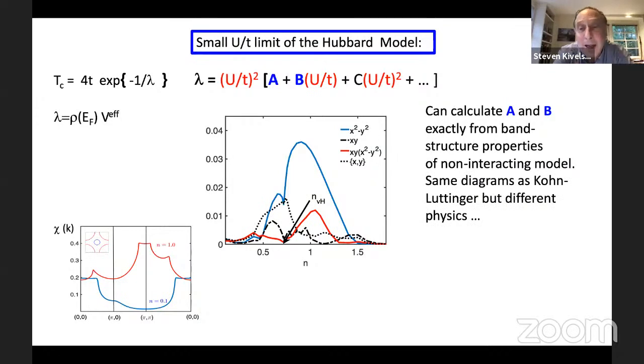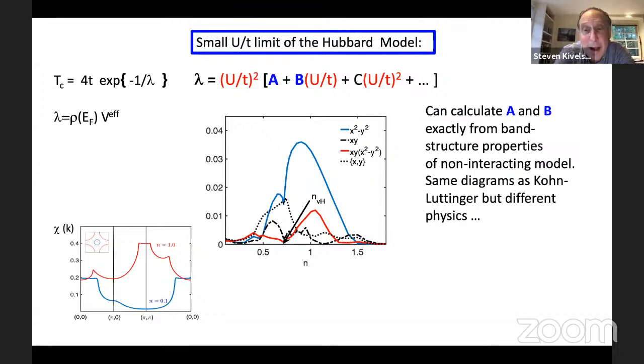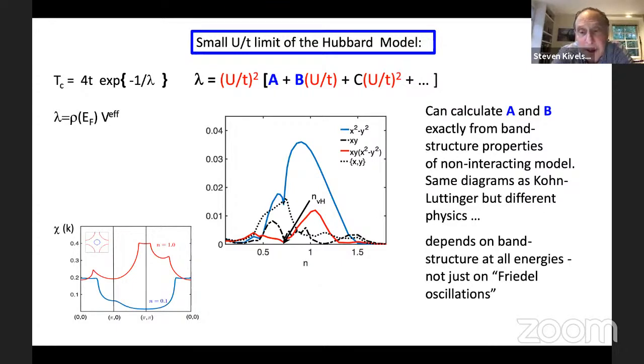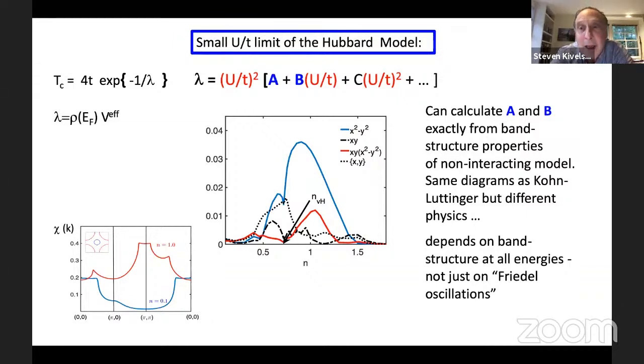This leads to an aside: the diagrams analyzed in this way are more or less the same as those analyzed by Kohn and Luttinger when they discussed this mechanism of superconductivity. There is a difference in emphasis — they focused on the effect of a sharp Fermi surface and Friedel oscillations as the source of pairing. That's not what's going on here. What's going on here is really a band structure effect: Chi is the real part of Chi, not the imaginary part, so it comes from all energies, not particularly focused on the Fermi energy.